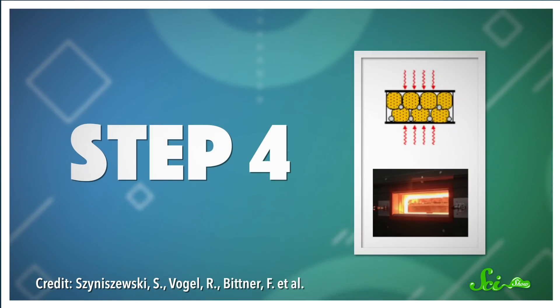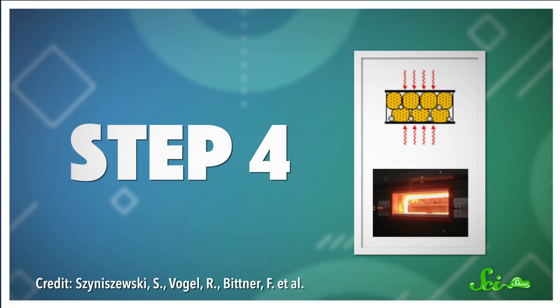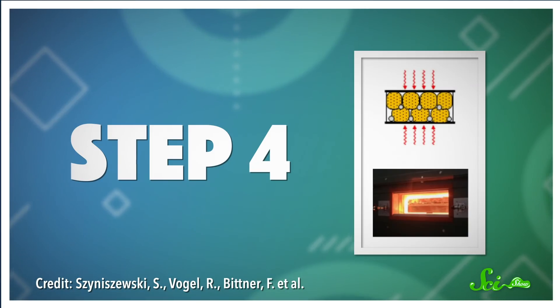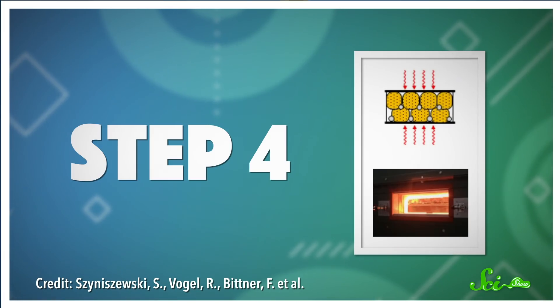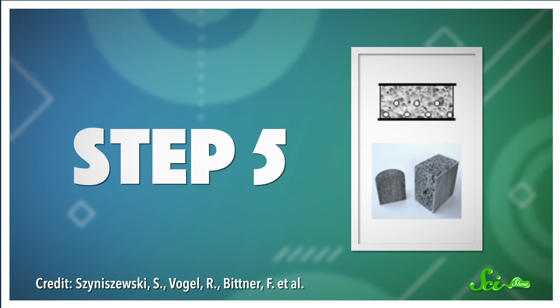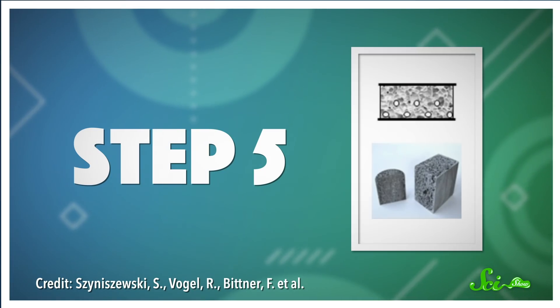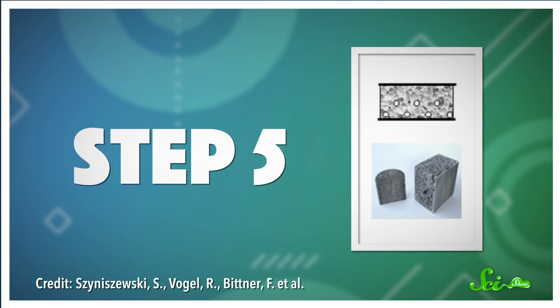And all this was then heated to 760 degrees Celsius. This caused the aluminum to melt, and the titanium dihydride to release all that hydrogen gas. Those bubbles made the aluminum expand out around the ceramic balls. Once everything cooled, the researchers were left with their new composite — ceramic balls encased in what is essentially an aluminum foam matrix.